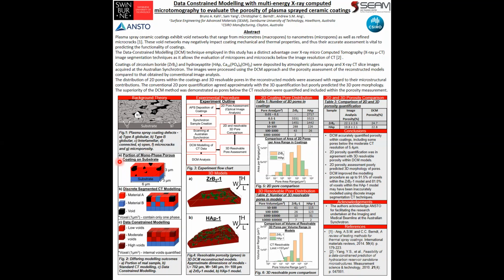This is illustrated in Figure 2, where a portion of a monophase coating on a substrate has undergone modelling using typical CT techniques and the DCM approach. Each voxel that comprises the CT model will be assigned a specific phase, even though it may be made up of several phases, including voids. Whilst in the DCM model, the voids within each voxel are assessed, allowing the evaluation of voids below the CT resolution limit. Thus, the work presented here demonstrates that the DCM methodology can quantify compositions within scanned samples that incorporate